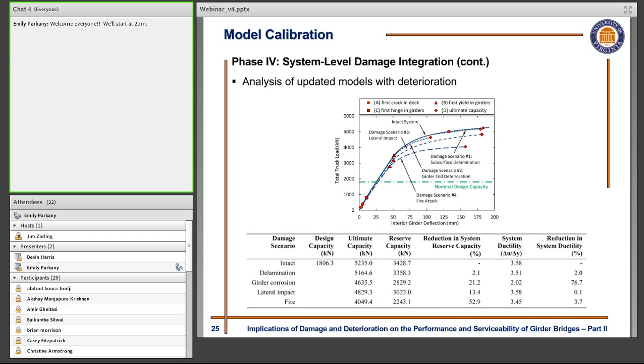And other than that, if you compare this reduced capacity with the nominal design capacity, you see that we also have reduction over the reserve capacity of the system. In some of the cases, we also have reduction in the ductility of the bridge superstructure, which can be defined as the ratio between the maximum deflection that the bridge can reach, and the level of deflection that the bridge experiences at the moment of first yield in the girders.